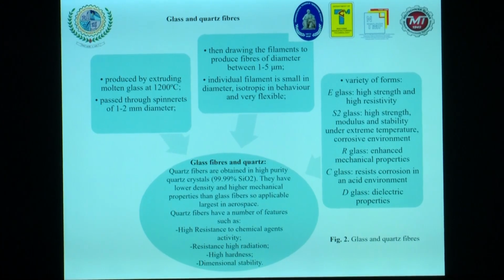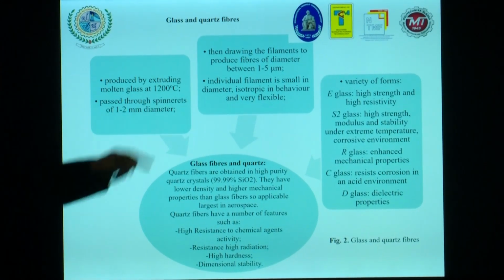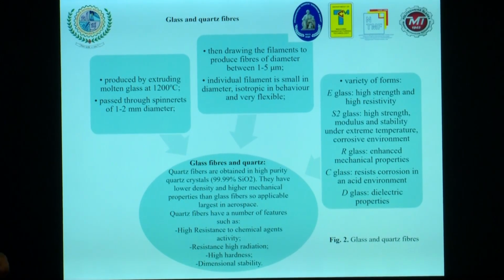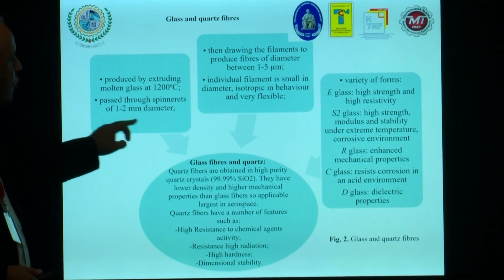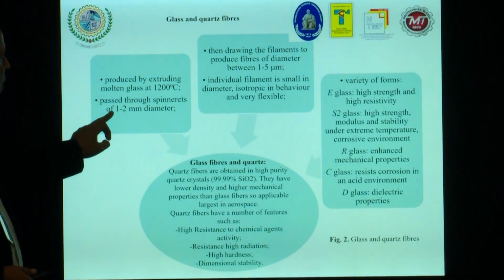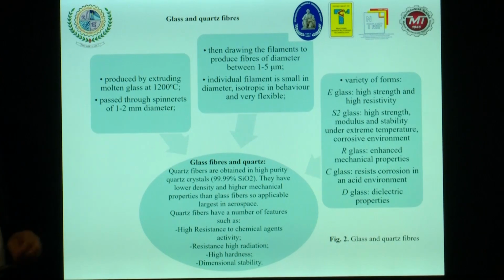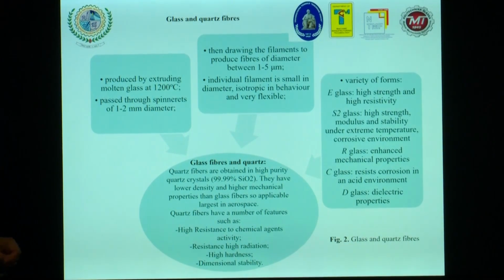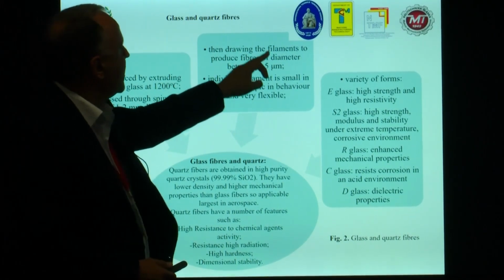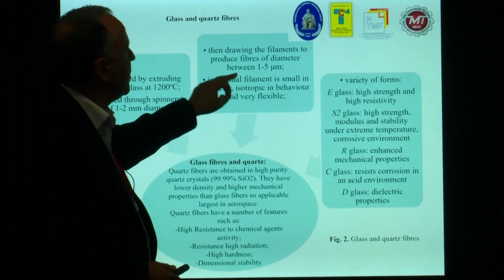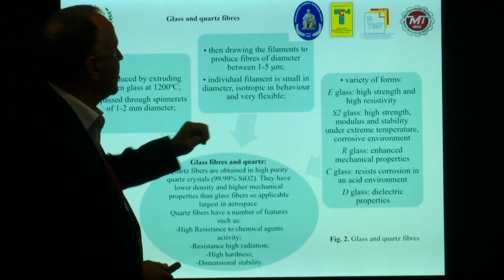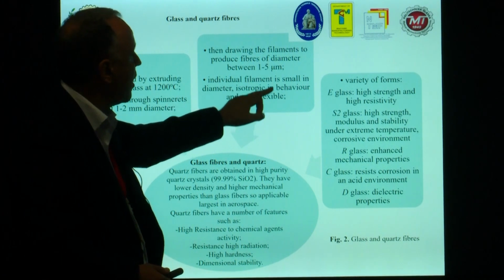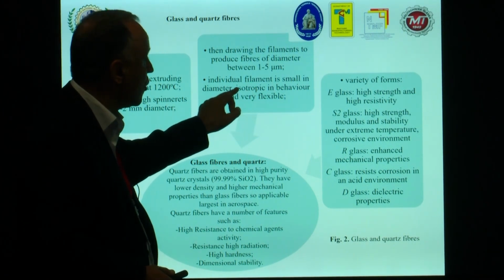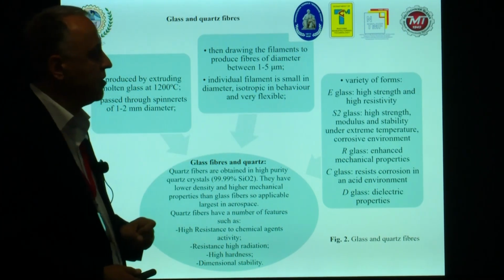Produced by extruding molten glass at 1200 Celsius, passed through spinnerets of 1 up to 2 millimeters in diameter. Then drawing the filaments to produce fiber of diameter between 1 up to 5 micrometers. An individual filament is small in diameter, isotropic in behavior, and very flexible.